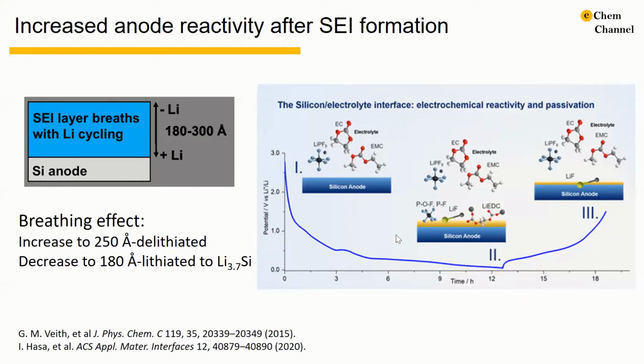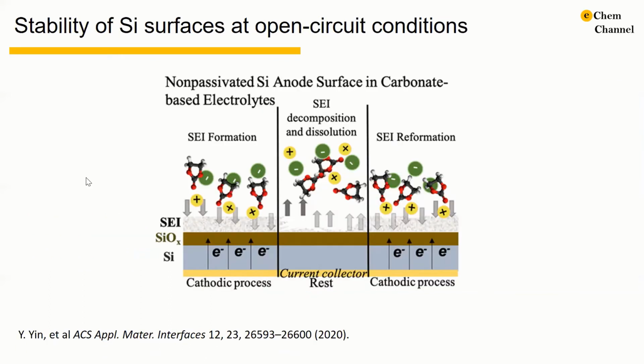The SEI breathing effect is found to be directly related to the formation of lithium ethylene dicarbonate, so this is from the solvent decomposition, and PF and POF containing compounds from the decomposition of the salt. These three types of compounds dissolve in the electrolyte, meaning they disappear during the lithiation process. In comparison, the lithium fluoride stays there permanently, representing a stable component of the SEI layer. Hence, during the lithiation-delithiation process, the thickness of the SEI layer keeps growing and shrinking, which leads to continual consumption of electrolyte with cycling.